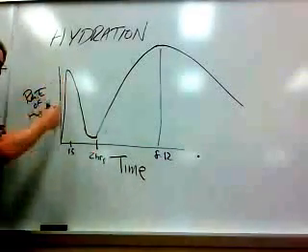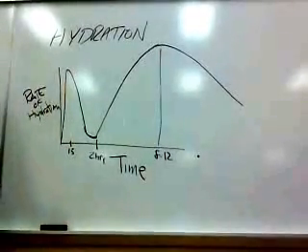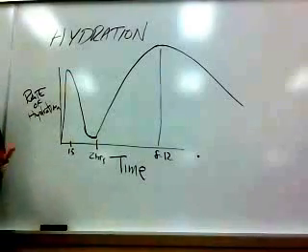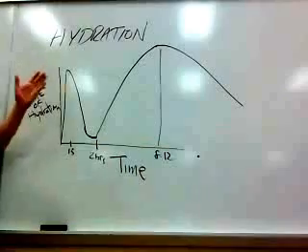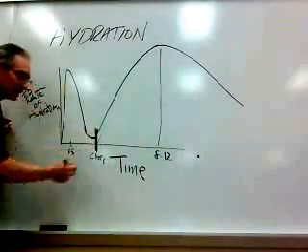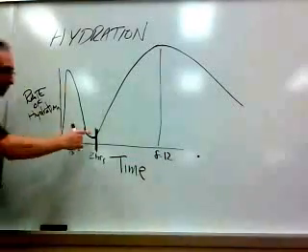This first hydration, they call it the aluminate portion of hydration, doesn't make it strong, doesn't harden the concrete. It's hydrating, it's just not doing a whole lot. Okay? You have until about this 1 to 2 hour mark to get the concrete in,